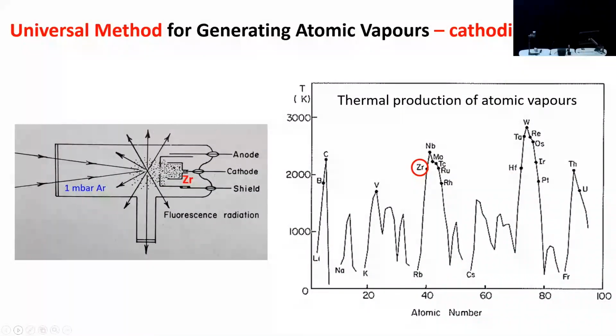So Alan suggested that I might look into another way of generating these atomic vapors instead of using a flame. Would it be possible to analyze a solid sample directly without having to dissolve it into solution? And the method used was to use cathodic sputtering, where the element of interest is made the cathode of a rare gas discharge. It might be argon, for example, and argon ions formed in the discharge bombard the cathode surface and eject atoms, in this case, say, zirconium, from the surface to produce an atomic vapor. Now, this is a universal method. It applies to almost any element in the periodic table, including these highly refractory elements here, which are very, very difficult to vaporize by thermal methods.